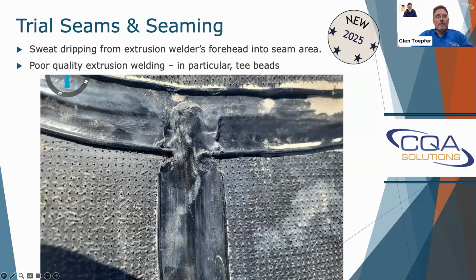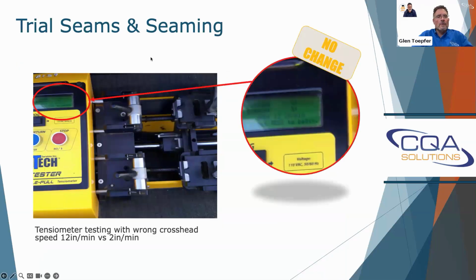But, moving on to trial seams and seaming, there's a few things here. We occasionally see sweat dripping from the extrusion welder's forehead into the seam area. That one was new, I didn't have it last year. We hadn't seen it in a while. People were doing pretty good, we'd get moisture, but not from the sweat. And that led to some poor seams that had to be repaired. And then, fairly common is poor T-beads. You really got to keep an eye on the T-beads. Your tensiometers, we continue to see this all over.